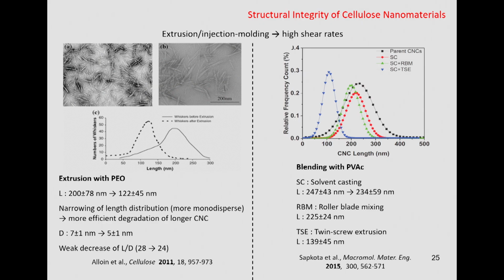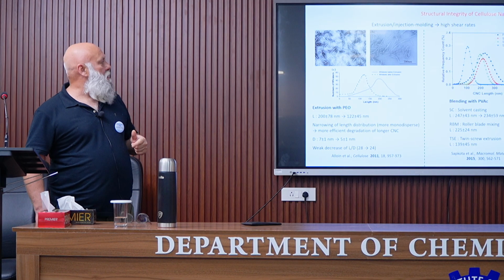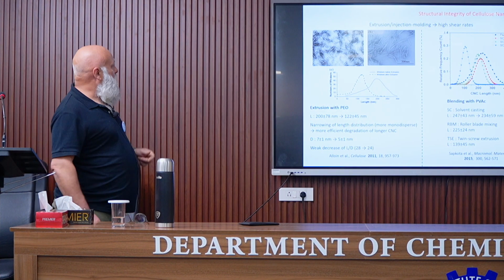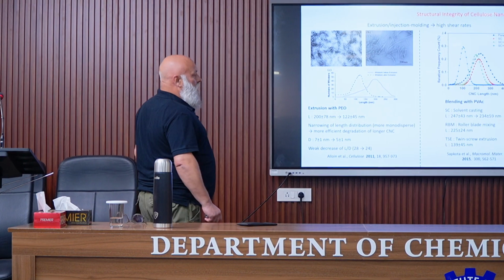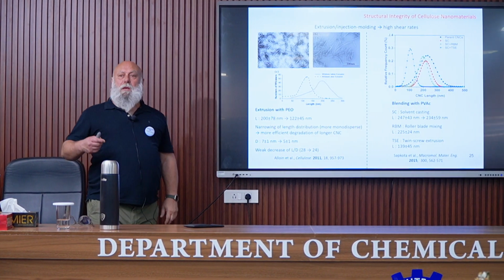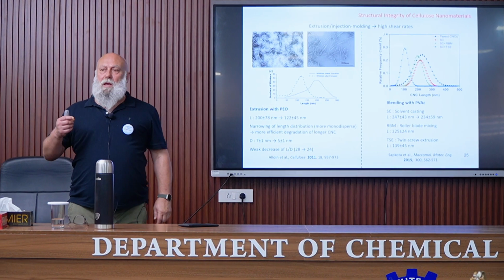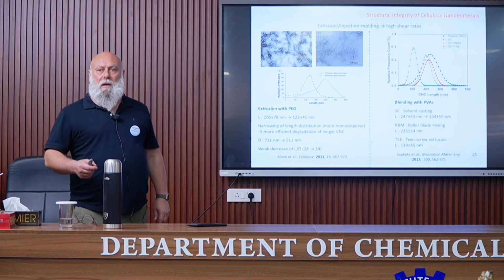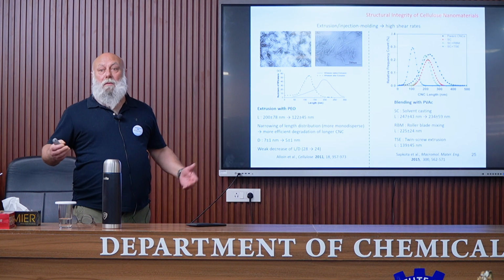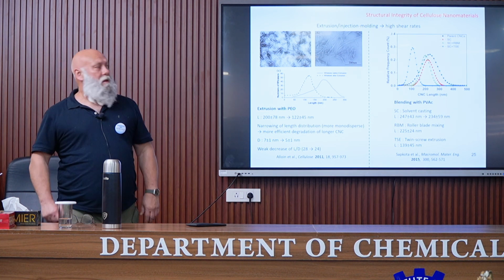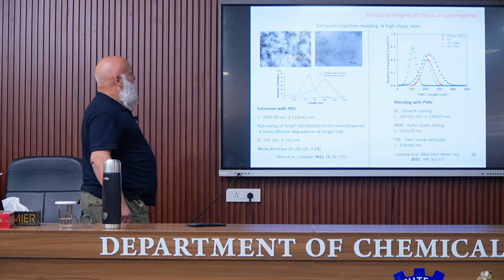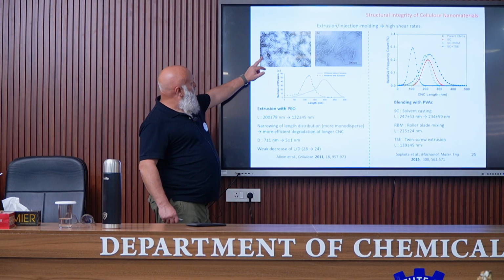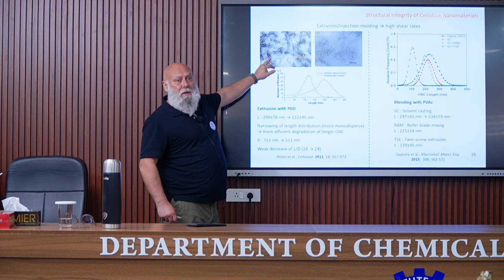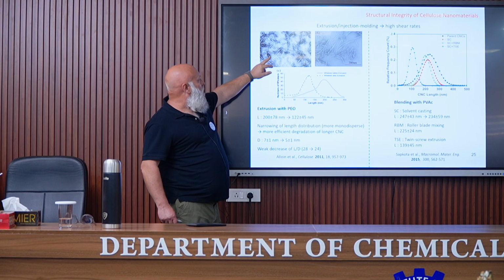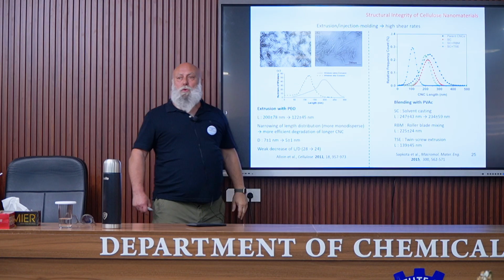So we have seen the drying of the nanoparticles that can be a drawback, the dispersion in the polymer matrix. The thermal stability and structural integrity can also be a problem. During injection molding or during extrusion, high shear rates are involved, meaning that it's possible to break the nanocrystals. And this was observed. This is cellulose nanocrystals before extrusion.